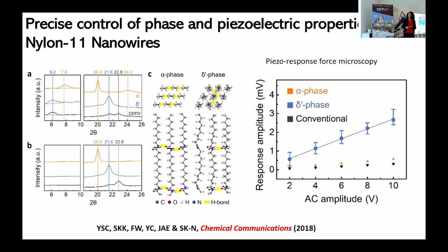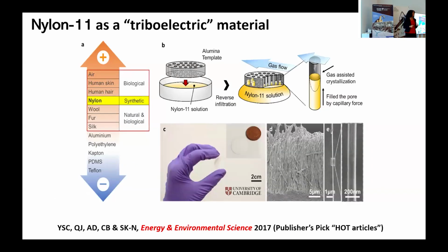Yonsik spent a lot of time trying to get the right conditions in order to make this delta prime phase. Again, you do not see this phase in the bulk or in the films, but only in nanowires. Then when we do piezoresponse force microscopy and look at the PFM amplitude as a function of applied voltage, the higher the voltage, the more the deformation. You can see that again, there's a clear winner here, and that's from our delta prime phase. That's another nice example of how you can control piezoelectricity in these structures.